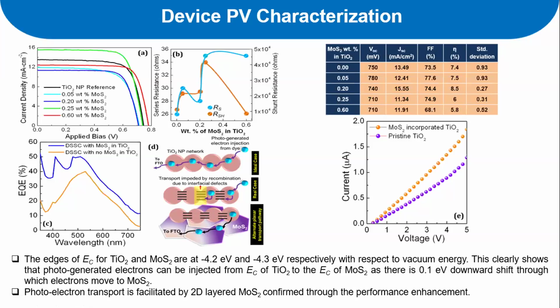And when we increased the presence of moly sulfide in the titanium dioxide to 0.25 wt%, the performance decreased, and when further increased to 0.60 wt%, we observed 5.8% photo conversion efficiency from 7.4. So this shows that for an optimum value of 2D layer semiconductor present in the electron acceptor, it increases significantly from 7.4% to 8.5. But if you further increase, that doesn't work that way.